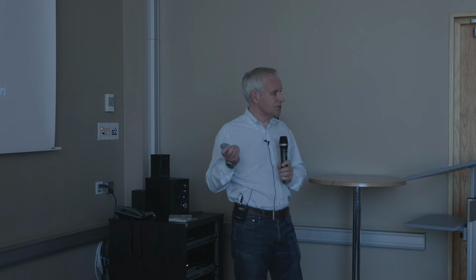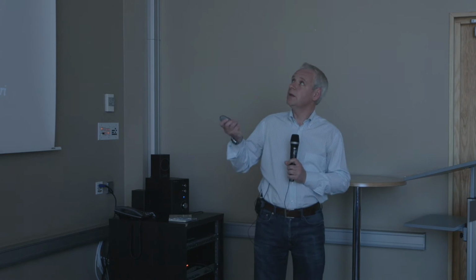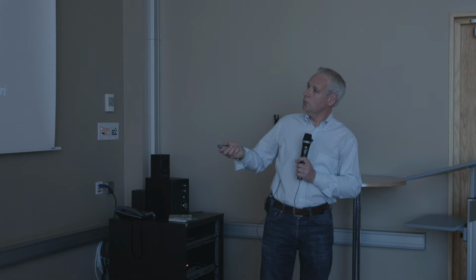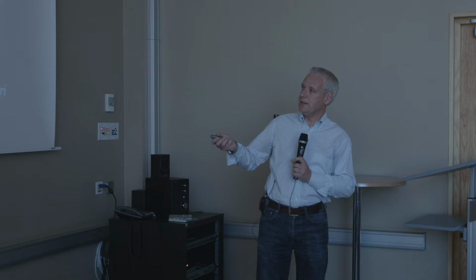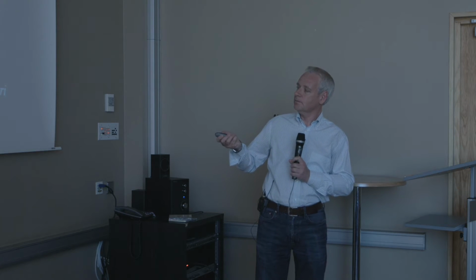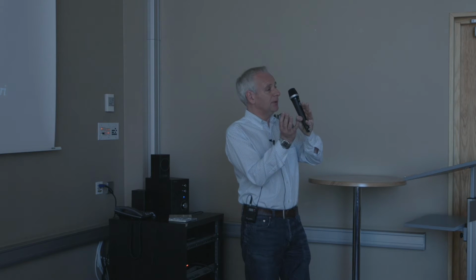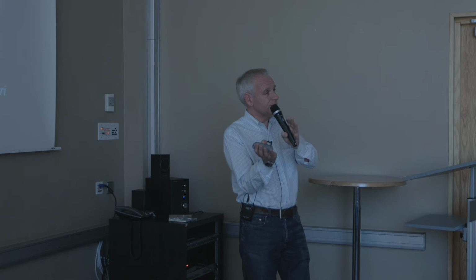But if we take a slice through their cuticle, this is what's causing the iridescence. So this is the very outer surface, where there's a slight angle here, the cuticle. And these layers, rather than being flat, are actually wavy. You've got a sort of slight sinusoidal arrangement going on, which means that the reflectors are actually angled slightly. And what that does, for each wavelength, is mean that the colour will be reflected over a broader range.